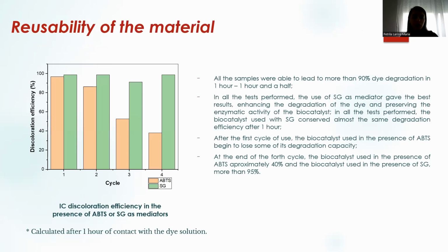Moreover, the composite biocatalysts could be successfully reused in several dye-degradation cycles. In the case of the composite biocatalyst used in the presence of ABTS, we observed a decrease in the degradation efficiency after the second reuse cycle, which was most likely the result of the adsorption of ABTS cation on the surface of the material, which is hindering the enzyme active site. On the other hand, when using the biocatalyst in the presence of syringaldehyde, we observed a 95% discoloration efficiency after the fourth reuse cycle.